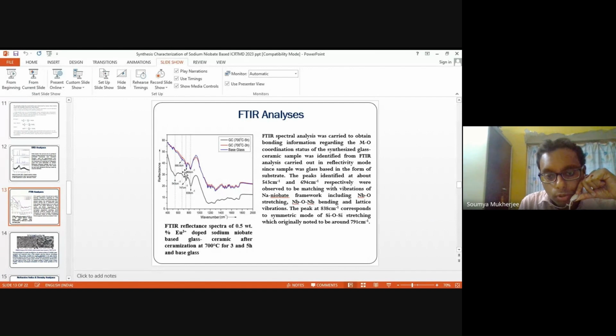The peak around 838 is actually close to silicon-oxygen-silicon, which is the framework within which the crystalline system will be developed. And the corresponding comparisons between base glass and the glass ceramics are also shown. There are slight variations because the base glass is based on sodium niobate, and it is getting transformed to crystalline, so there is no drastic change of metal oxide coordination. The chemical composition is almost the same. That's why no such drastic changes are observed.